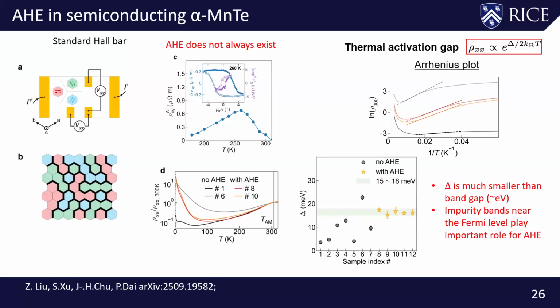Again, let me show you the earlier result: we have this hysteresis loop, and we reproduced the hysteresis loop that was shown before. But the problem is that the hysteresis loop we found in these earlier samples is not completely reproducible, in the sense that we looked at, I mean, this is at an earlier slide, a total of 13 samples.